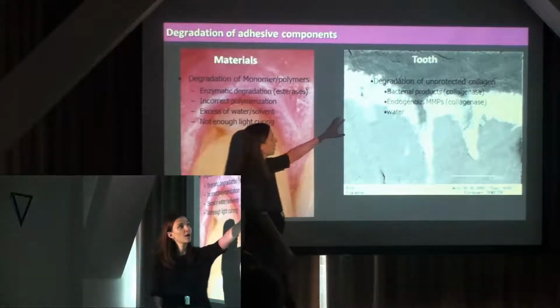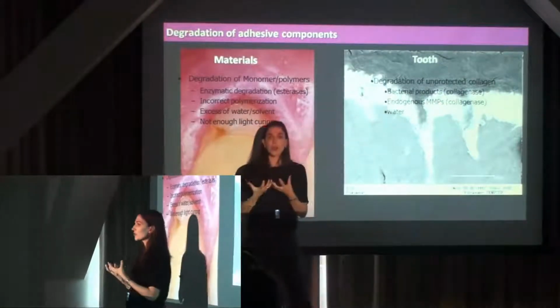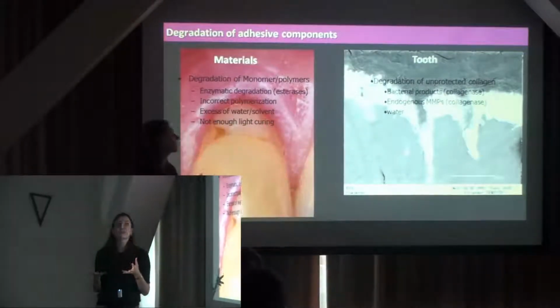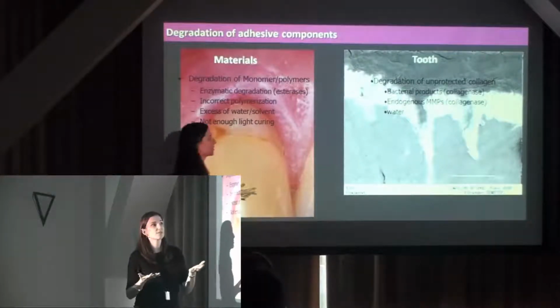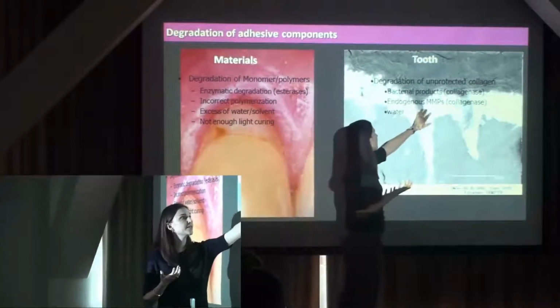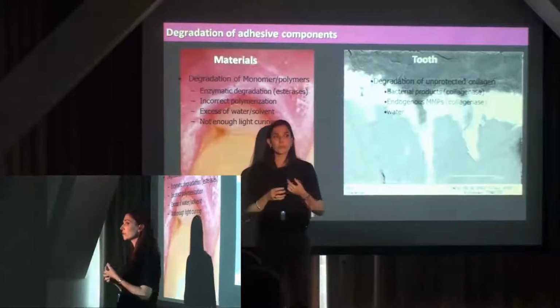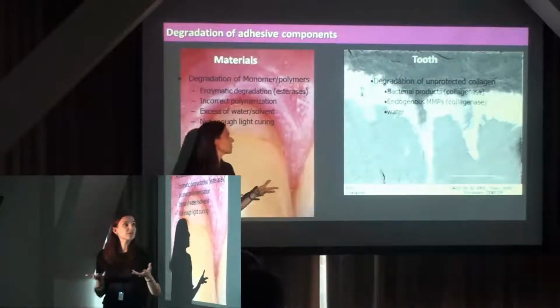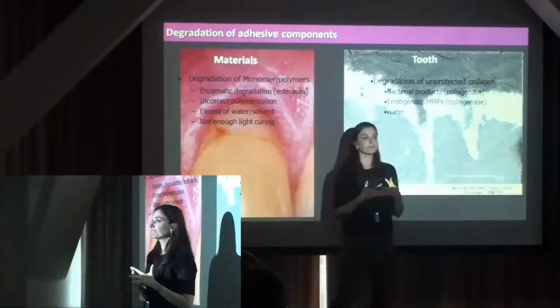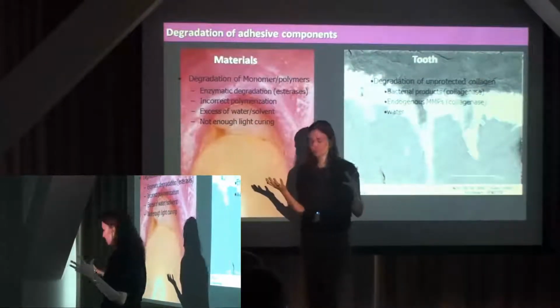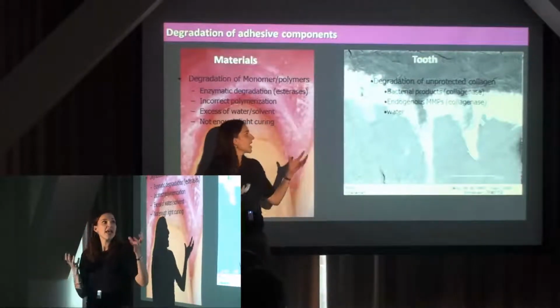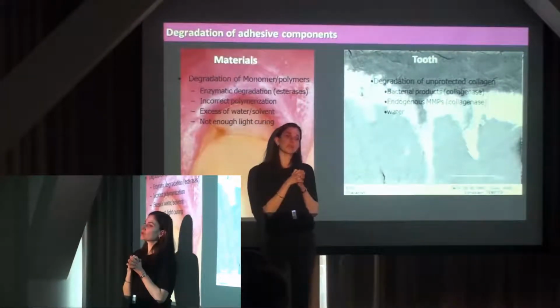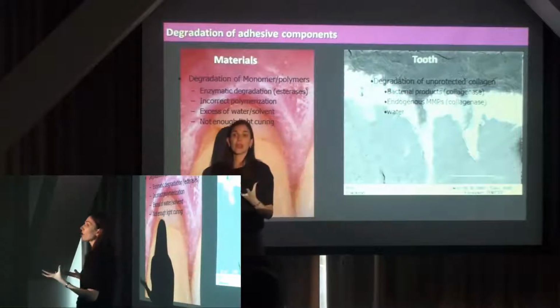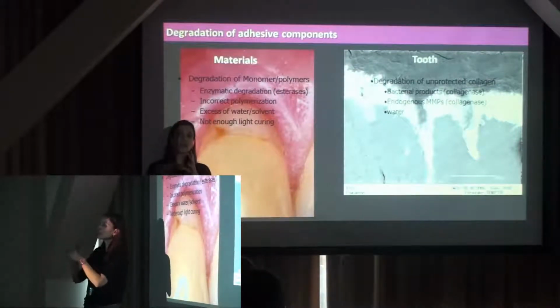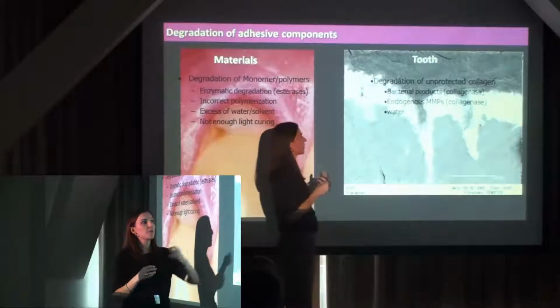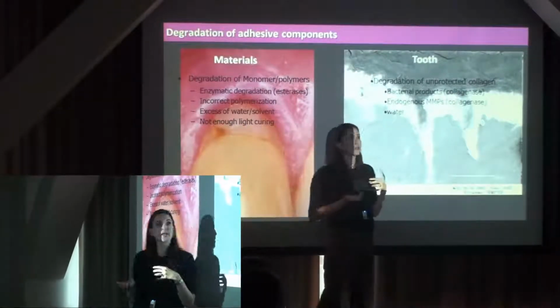On the tooth side, the biggest problem is that that collagen that's so important for us is slowly degrading. And it can degrade by two mechanisms. So we have matrix metalloproteases. Are you guys familiar with matrix metalloproteases? So matrix metalloproteases are these enzymes that we have a big family of, and they are similar to collagenase. So this basically has the ability to break down collagen very easily. Depending on the type of MMP that we have around, this process can be slightly quicker.